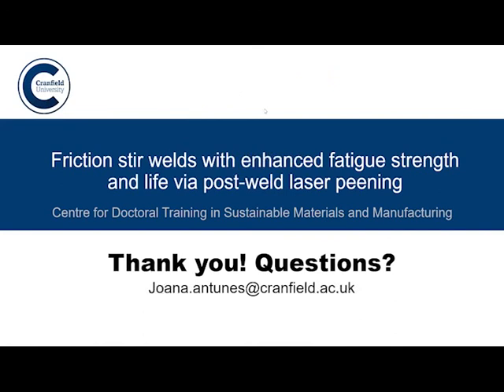Okay, yeah. So a lack of penetration defect is very similar to what's traditionally called a lack of fusion defect in welding, but it can't be called a lack of fusion defect because, as I said, there's technically no fusion in the process. So if you think about two plates being joined together and you have the tool rotating on the top, the friction from the rotating tool will generate quite some heat input, and that energy essentially needs to travel throughout the whole thickness of the material. If it doesn't do so accordingly, which depends on the friction stir welding parameters, then you will have an incomplete bonding of the two plates on the opposite side of the tool, which is the root side, as I said. So that's essentially what a lack of penetration defect is.